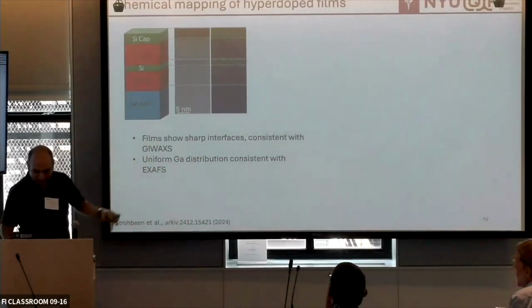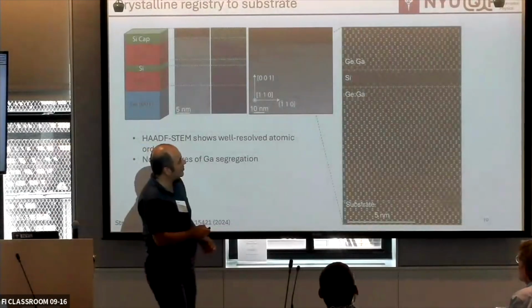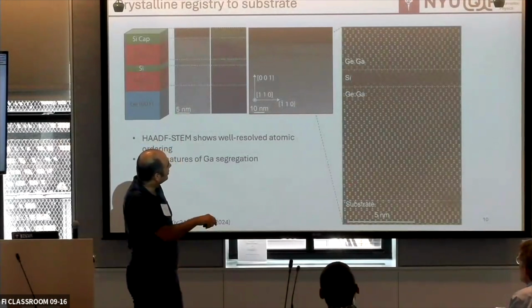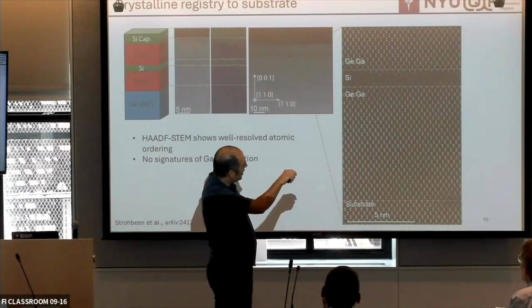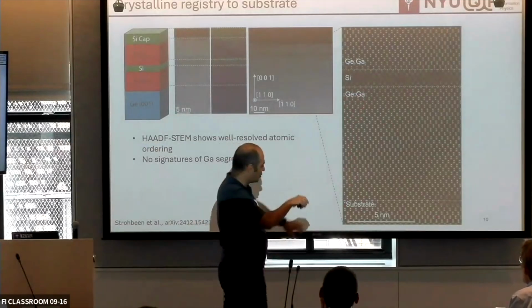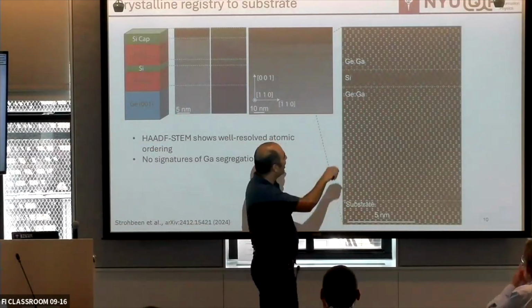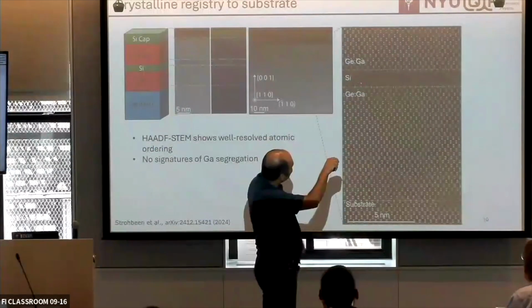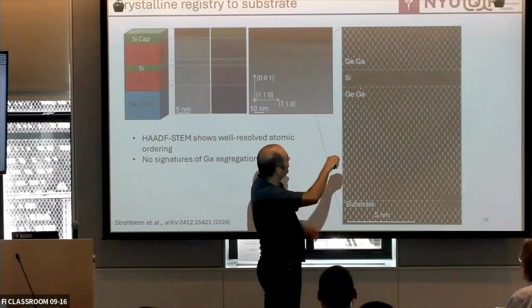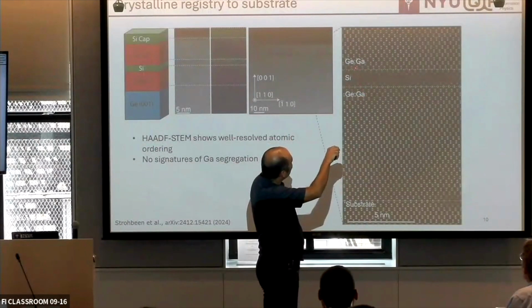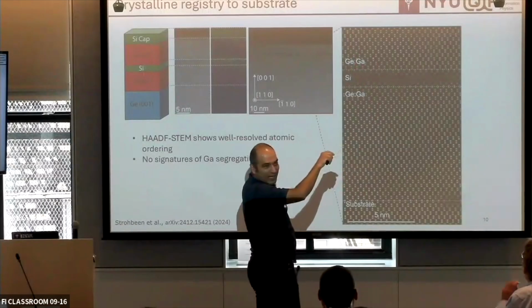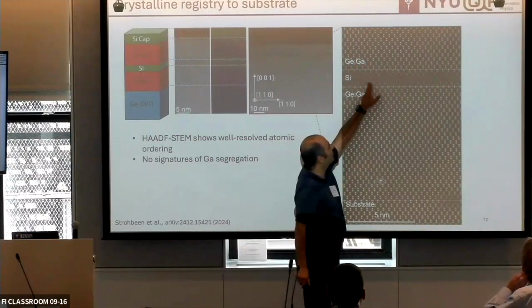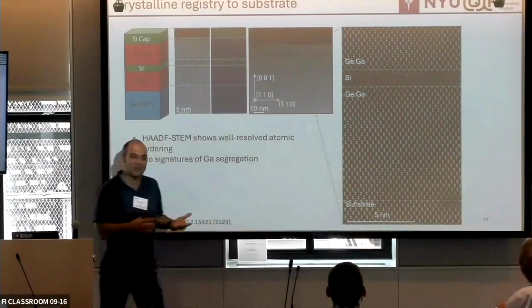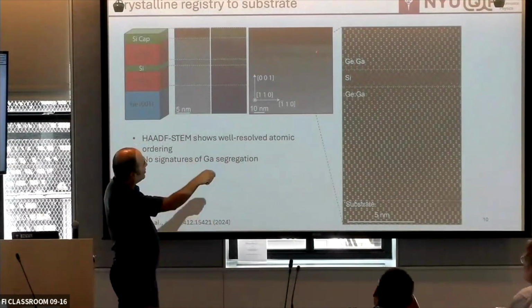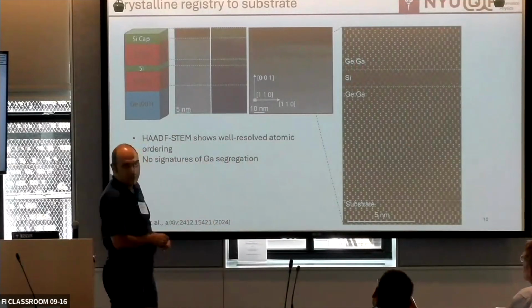But you spend more money, you talk to your best friend who's a TEM person, aberration corrected. Now you can look at this. So basically, this is the substrate. This is the doped gallium in germanium, which almost looks identical to this lattice. And then this is where we switch to silicon, which follows the same pattern actually, because it's also the same diamond structure. And then we dope gallium again, and you almost can't say, except for the small variation of the intensity, where is actually the junction, right? And the surface, as you can see from the zoom out, is just quite free, right?